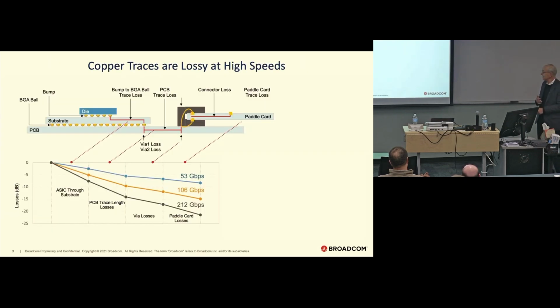So the copper problem is here. Today all these interfaces are 200, 400, 800, 1.6 terabits. And copper loss at 200 gigabits is over 20 dB, just to get from the die out to a card. So that's really pushing photonics in here, and that's what we'll talk about today.